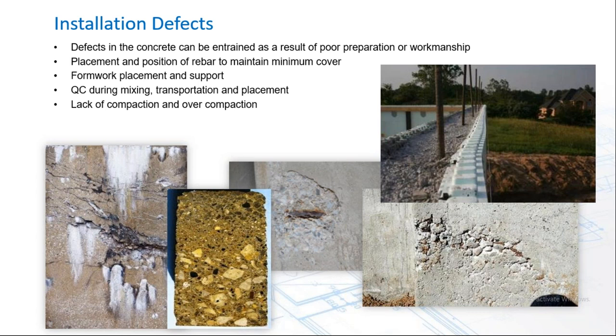across that cross section. A lack of cover, as I mentioned, with the positioning of formwork, really leaves the rebar exposed very near the surface. Under compaction, we can end up with honeycombing, bug holes, and things like that. Obviously, reducing our effective cover over reinforcing, but also a gateway for contaminants to start their entrance into the concrete. And ultimately, we end up with things like spalls, but also efflorescence, where soluble salts are washed out of the concrete matrix.